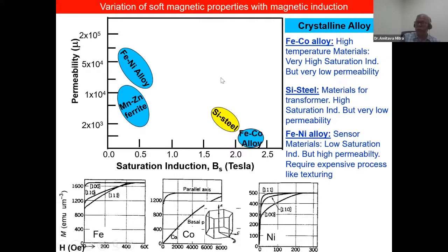But by adding a foreign, non-magnetic element, you will lose one property: the saturation induction of the alloy. The elements being added do not contribute to the magnetic property in that sense, since they are non-magnetic materials. They do contribute to magnetic properties in a different way, but they will not contribute to saturation magnetization, because they have no magnetic moment.